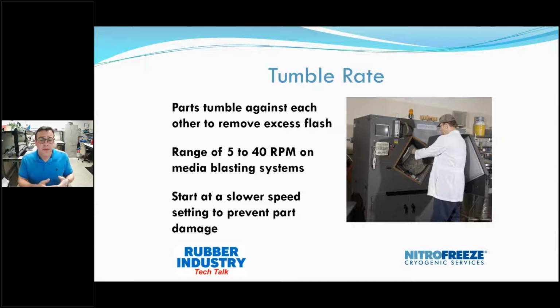Again, even when you're using a cryogenic tumbler, you should probably also start at the low side. You don't need much, I find, around say 10 RPM is a good speed on that one. So you probably want to start at about 25% of whatever your total power is for your revolutions per minute on that kind of machine.